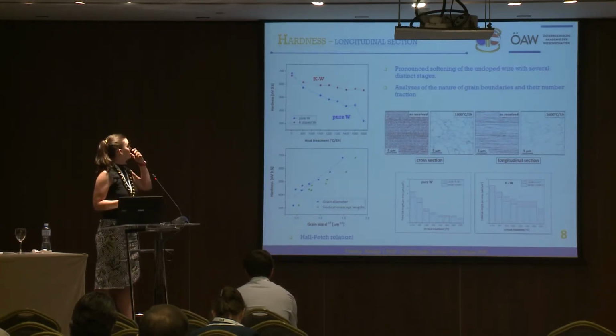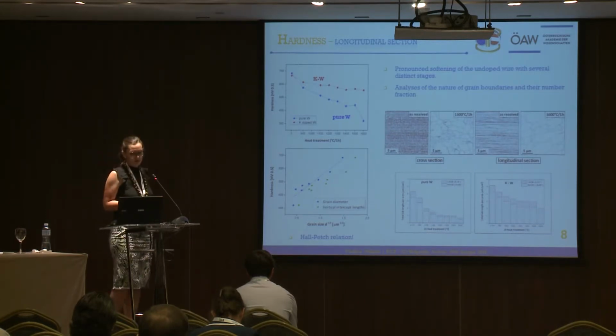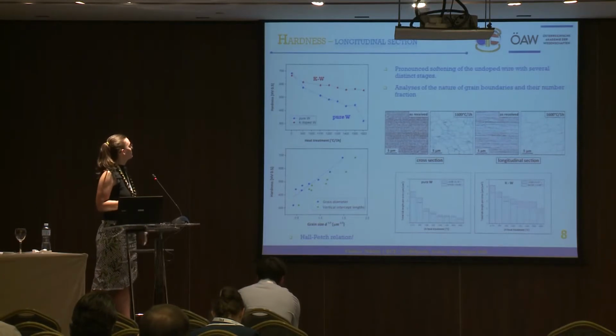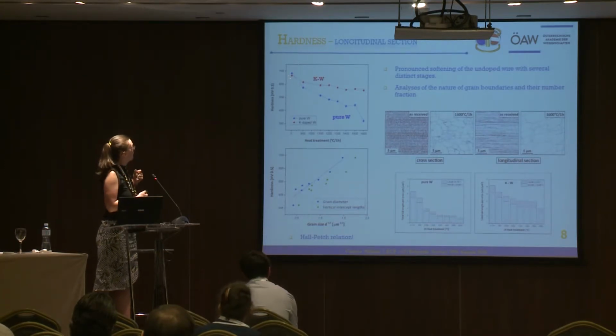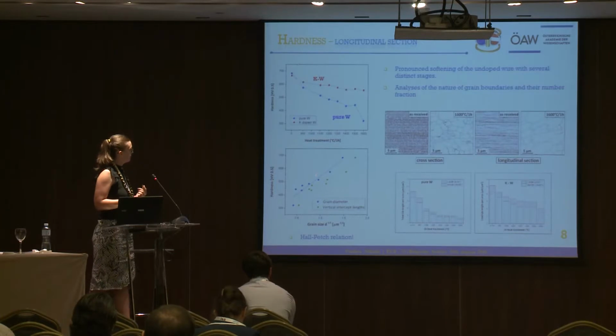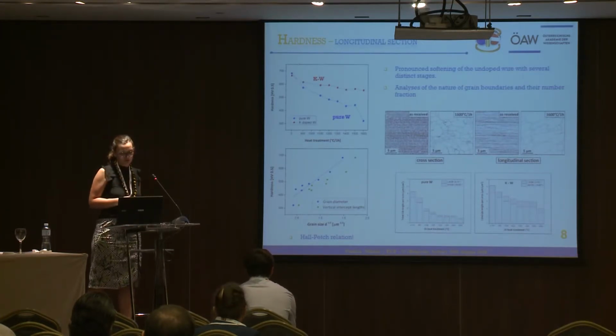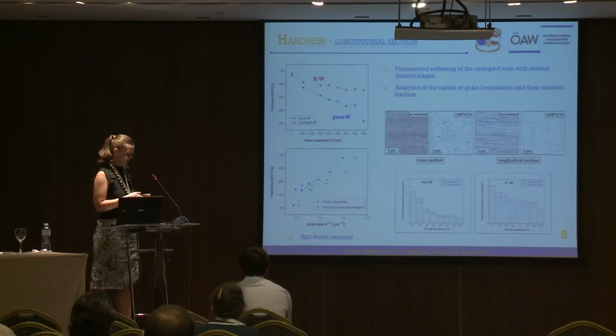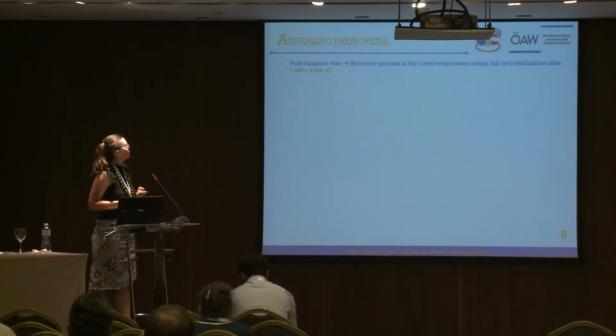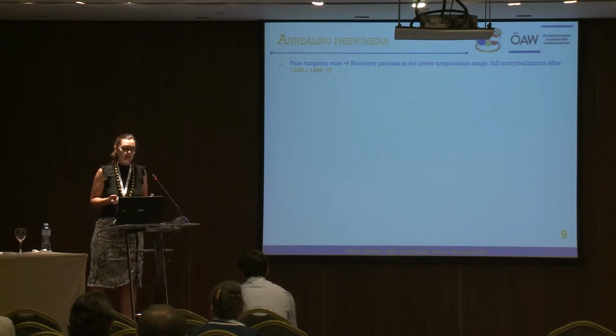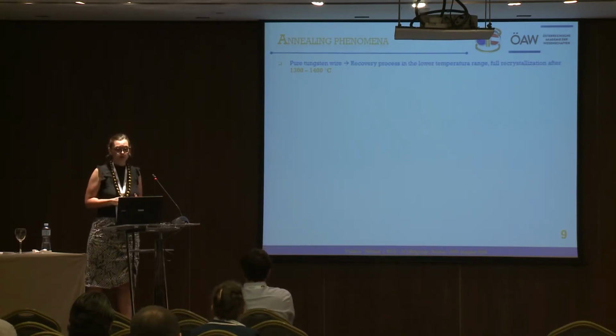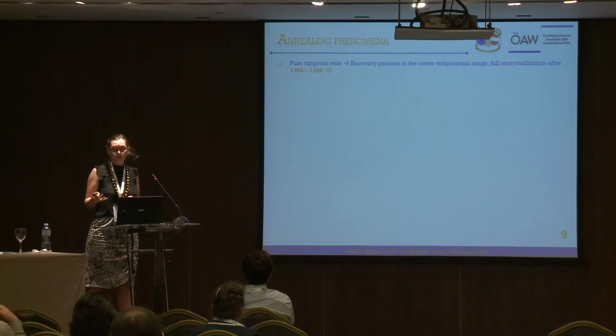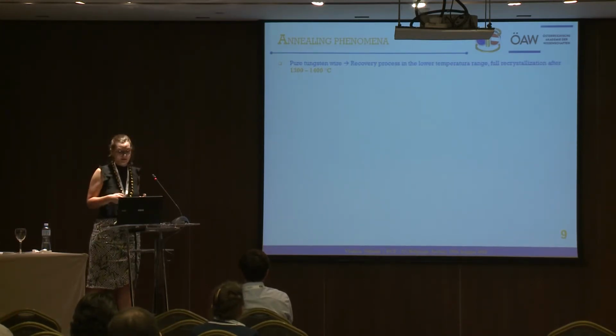And the final information that we obtained regarding the microstructural stability was hardness measurements, where we can also see the softening effect pretty pronounced for pure tungsten and not as pronounced for the potassium doped one, and we could even correlate with a linear relationship the hardness and the grain size in this plot. Okay, so to summarize this part, we can say that pure tungsten already at lower annealing temperatures undergoes recovery, and in the range between 1300 and 1400 degrees C, it is fully recrystallized.